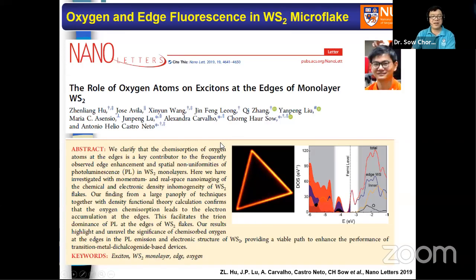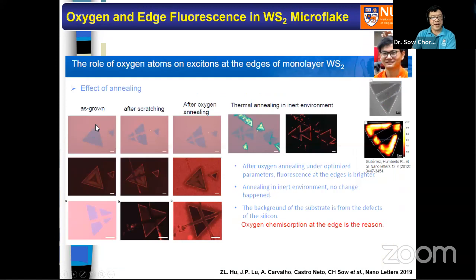It's a very simple experiment we can show you. For example, here's a picture of a triangular-shaped WS2 we grew on the substrate, okay? And then you can capture the fluorescence of the edge very nicely in this way. So for example, here, the picture at the bottom row, you have a triangular-shaped WS2, and Zhen Yang intentionally used a penknife to scratch the middle, okay? And after the scratch, you look at the fluorescent microscope picture, you see that, okay, still only the original edge gives you red fluorescence.